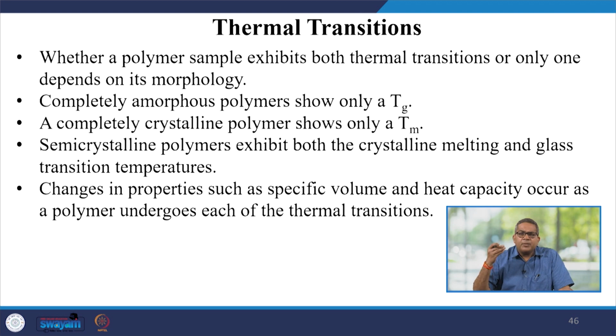Whether a polymer sample exhibits both thermal transitions or only one depends on its morphology. If it is a completely amorphous polymer, it shows only Tg, the glass transition temperature, and a completely crystalline polymer shows the Tm. A semi-crystalline polymer exhibits both the crystalline melting and a glass transition temperature, so it is in between.